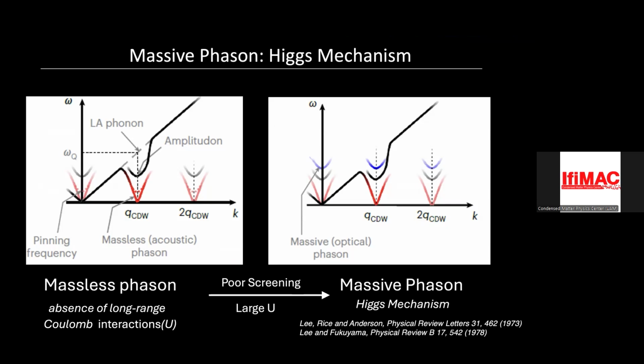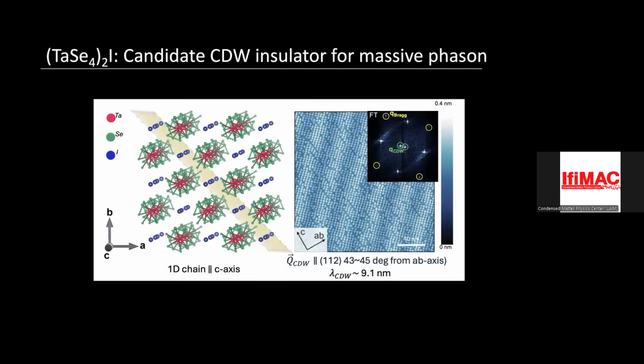So this was predicted in the 1970s. There were a series of papers really in the 1970s about this mechanism to provide mass to the phasons. But the problem has always been that it's really hard to find insulating charge density waves. So now that brings me to this compound, tantalum selenium iodide. Tantalum selenium iodide, it turns out, is a very, very, very strong insulator. In fact, for STM people, we can't go much below 70 Kelvin, right? If we get below 70 Kelvin, we can't tunnel, we can't do anything with this.